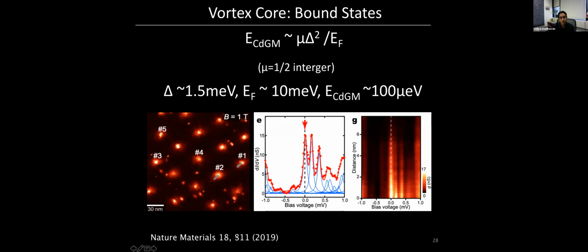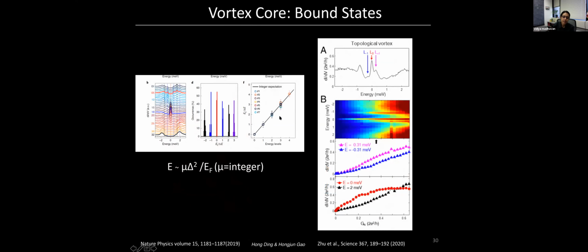Interestingly, if you're interested in this vortex work, you can also see that what he shows is that if you go to very low magnetic fields, a much larger percentage of the vortices show 0 bias states. And as you increase the magnetic field, the number of 0 bias states actually goes down quite dramatically. More recently, Hong Ding and Hong-Jun Gao have done two important pieces of work on these vortex bound states. One is that they've shown that